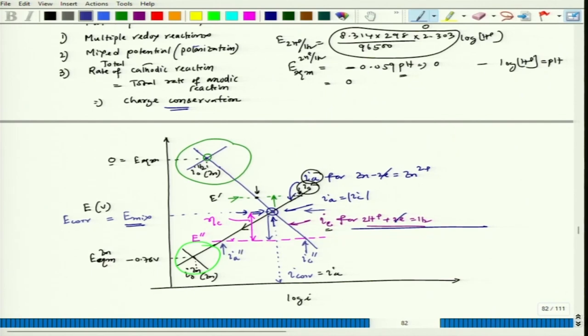So, now if I can take the potential to this E double prime by having this over voltage of this amount, I could see that IA double prime is very, very less as compared to I corr, and then definitely my corrosion rate or dissolution rate would go down. Now, this dissolution rate is going down because of what? Because of cathodic polarization or because of sending negative current to zinc. Okay. So, then I take the potential down from that E corr, and then I can experience a very, very low corrosion rate compared to the rate of zinc dissolution when the potential was at E corr.